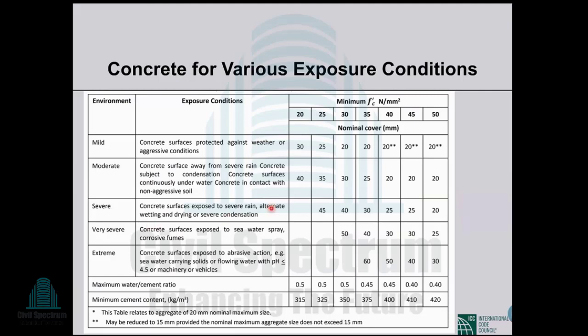So for severe condition, in case of Bangladesh, in most of the structures, the outside concrete is always exposed to severe rain. Actually, if we follow this table, although in different places it is mentioned that minimum concrete strength is 20 megapascal or 17 megapascal if the structure is 4-storied or less, because of the environmental condition, we cannot actually go for 20 megapascal. We need to go for C25 class concrete, 25 megapascal concrete.